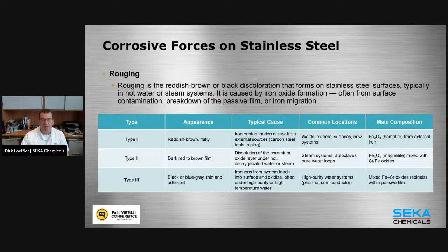Type 2 is a little bit more difficult. Here we're generally talking about the passive layer failing. We see this a lot with hot water application, steam, or deoxygenated water. So this is something that is more severe, more difficult to remove. Sometimes it cannot be removed at all, at least not chemically. And generally here we're dealing with what we call magnetite. So it's a ferric oxide type of material that is also mixed with chromium or additional iron oxides. As a general rule, all rouging is iron oxide, just different types and different degrees.